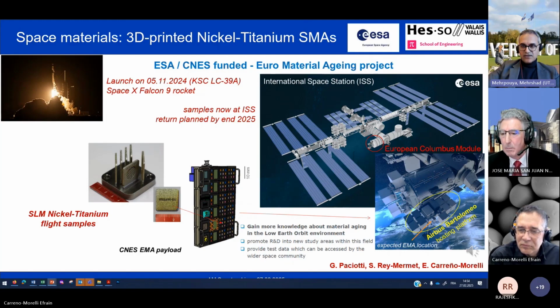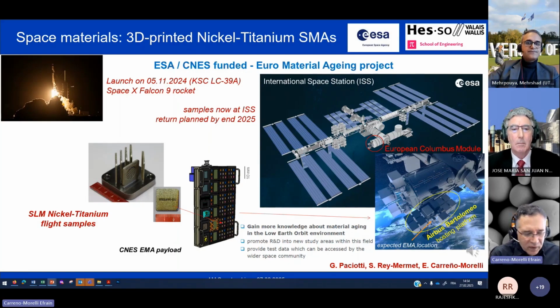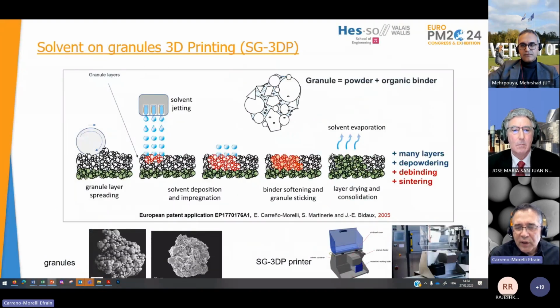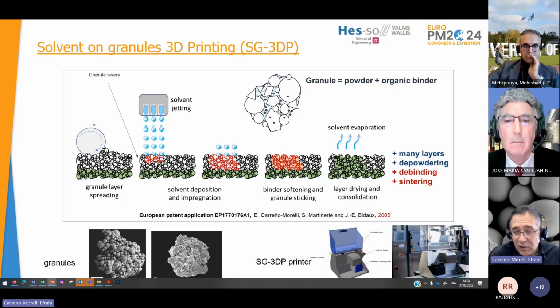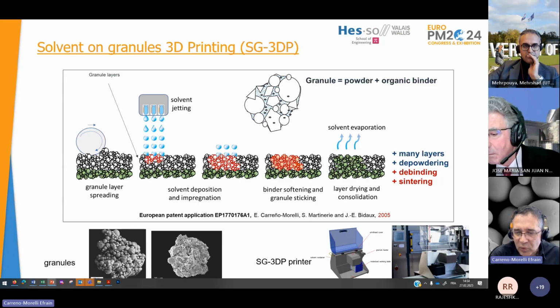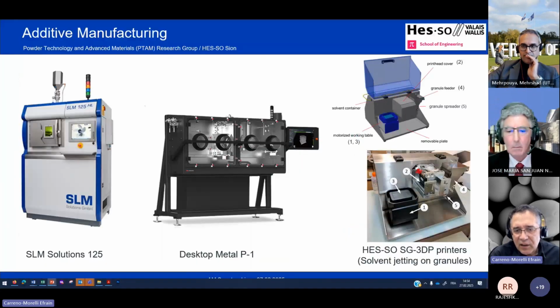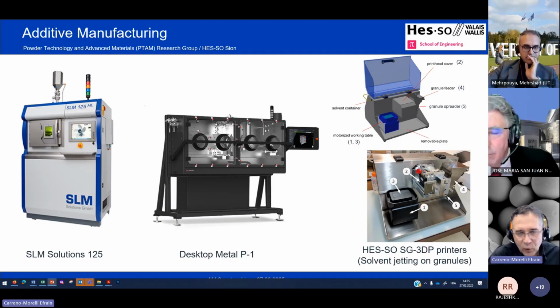Do you need an inert system to print NiTi? How much oxygen level in ppm is required? It's from Chen. Yes. When we use the solvent on granular 3D printing, we perform it under air without any inert system in the printer. We take care in powder handling and also in strict debinding and sintering conditions, but the printing itself was under air. This is probably not the best, but with our prototype, we cannot do more than that. With devices like the Desktop Metal P1, one can work under a protective atmosphere, and we have not worked with that until now.